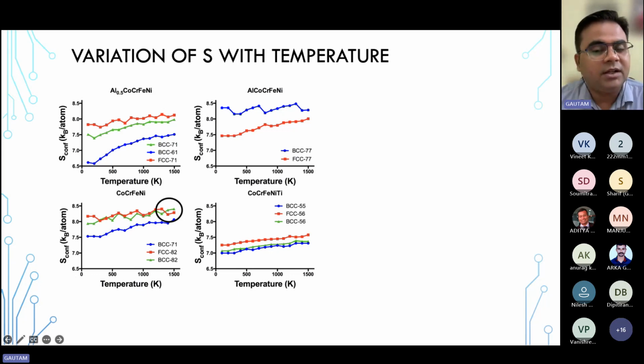Aluminium, cobalt, chromium, nickel shows that BCC is a stable phase, but it shows a decreasing trend. I mean, even though the FCC parameters seem to be increasing, this seems to be more or less constant. And the interesting thing is that for cobalt, chromium, iron, nickel, titanium, again, FCC is stable, but its value is very low in comparison to the other cases which we saw. And we saw that intermetallics can form easily in this particular case.